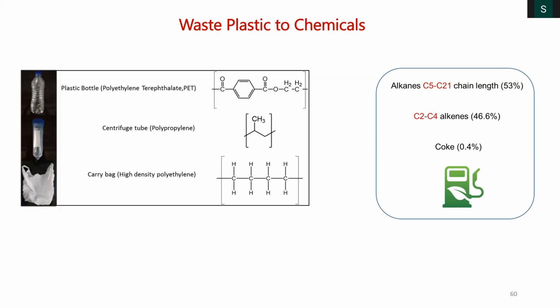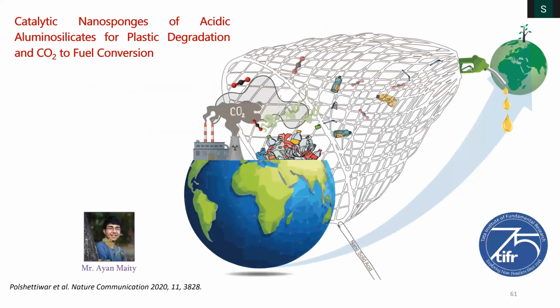But can we make it sustainable? Can I degrade these plastic bottle at a lower temperature using some catalyst and make this process sustainable? And that's what we recently showed, that we prepared a solid acid whose acidity is as strong as like a zeolite, but zeolite is microporous material, issue with the diffusion, whereas this is a mesoporous material, bigger pores and pore size distribution. So we came up with a new solid acid which has a porosity like aluminosilicates, amorphous aluminosilicate, but acidity like zeolites. And combine these two factors, we showed that one can degrade the plastic, even the CO2 reduction to dimethyl ether.